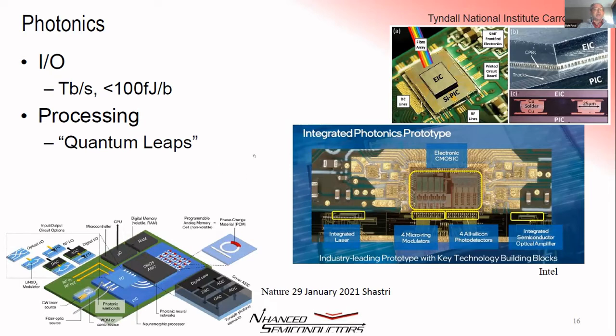transmission. This has been demonstrated at this point by numerous companies. Tyndall has these parts that they've built and shown. Here they're actually putting them together with solder bumps, which turns out to be one of the highest power consumers in these assemblies. It is very common. Almost all the devices that we see, you have an electrical IC, which typically is done in a very deep submicron process because you have SerDes that are running at 25, 32, 56, now 112 gigabit data rates. So you have to do them in ever smaller geometries.